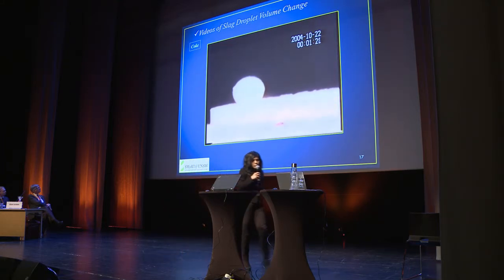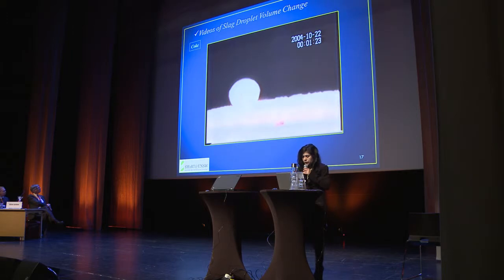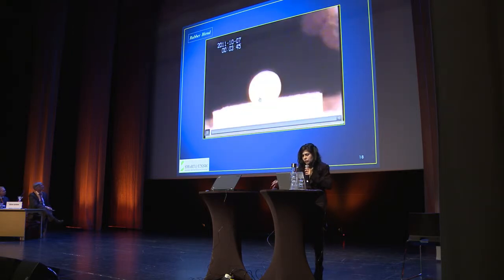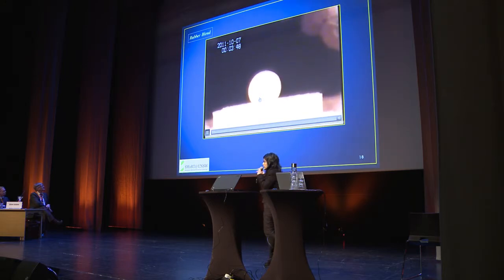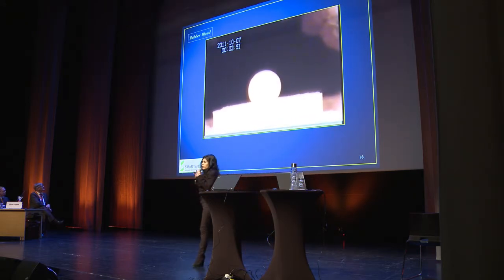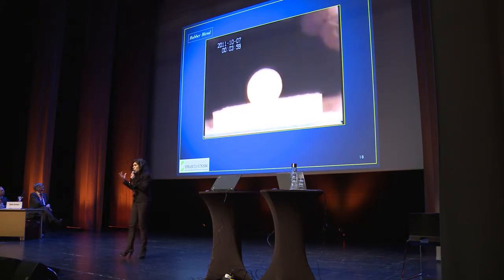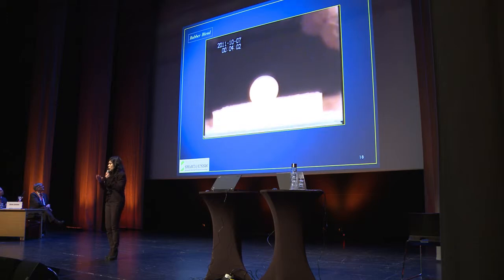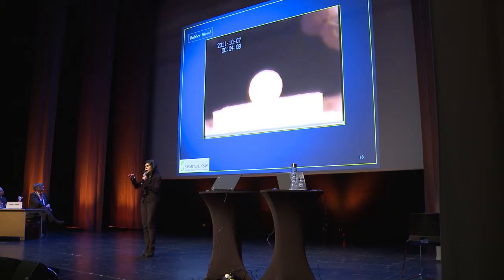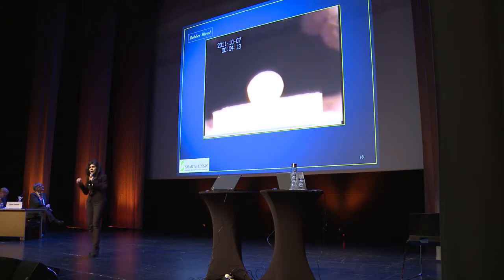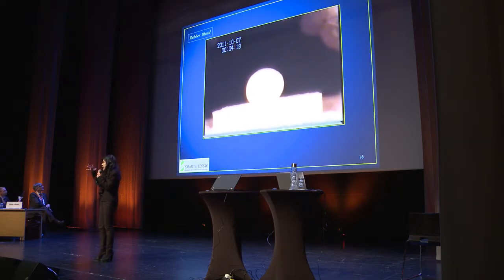Now, compare that with the next video, and I'll just play that real quickly as well. This is the one where we've blended in rubber. So same experiment. The substrate has now got a blend of rubber tires. We've now got the same slag at 1550 degrees Celsius. The reaction as it's starting to happen that you can see there is quite different to the previous case. And what I mean by that is you can actually start to see visually how that slag foam is indeed growing with time. And of course, what that is indicative of is that the gas bubbles that are being generated as a result of these high temperature reactions are actually being sustained inside the slag foam.